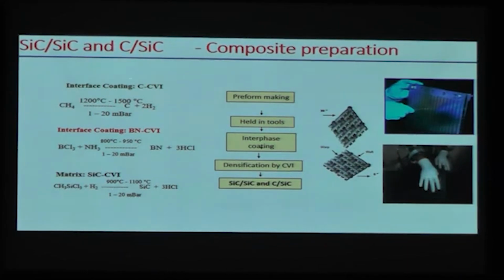And first we will go for the interface coating by cracking methane. So there I get the pyrolytic carbon. And in some cases boron nitride also we can take. BCl3 and ammonia will be reacted to get the boron nitride. And finally the matrix CVI, by taking methyltrichlorosilane, which is decomposed at high temperature to get silicon carbide. So this is a typical process flow. And this SiC/SiC means silicon carbide fiber is used as a reinforcement, rest all same.